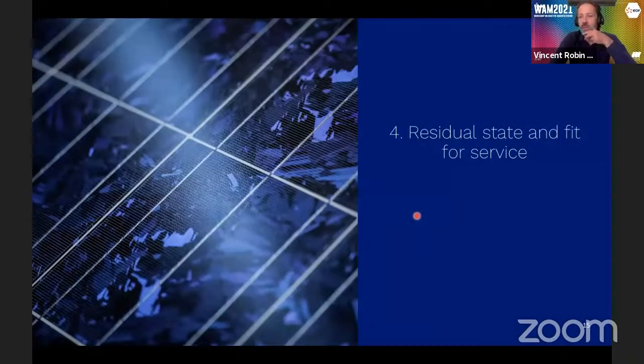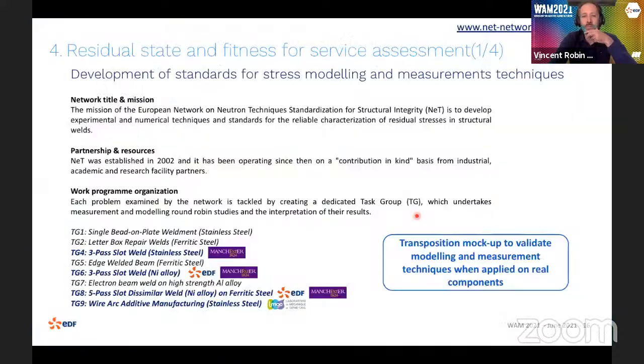So the last part of my presentation before the conclusion concerns the use of residual stress for engineering purposes. And we have been working on this for a long time. EDF has been involved for a long time in an in-kind contribution project driven by the European Commission, which is called the NET project. This project has the objective to develop standards for stress modeling and measurement techniques. And within this project, we are working in task groups, and EDF is managing two task groups, one on multipass weld nickel-based alloy, and one other for welding repair on ferritic steel.